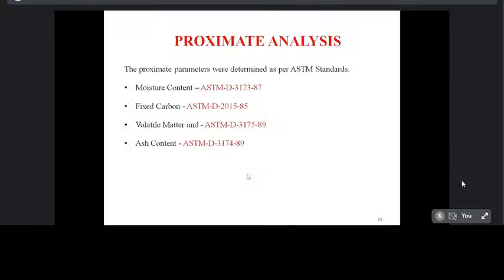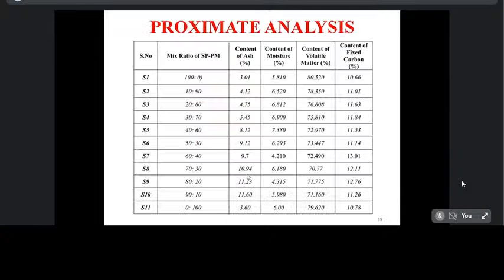So the next one is the proximate analysis. In this produced biomass briquette, we have taken all the produced biomass briquettes for their proximate analysis as per ASTM standards. Moisture content ASTM D3173-87, fixed carbon D2015-85, volatile matter ASTM D3175-89 and ash content ASTM D3174. So this table shows the proximate analysis of the produced biomass briquette for the content of ash, moisture, volatile matter and fixed carbon.